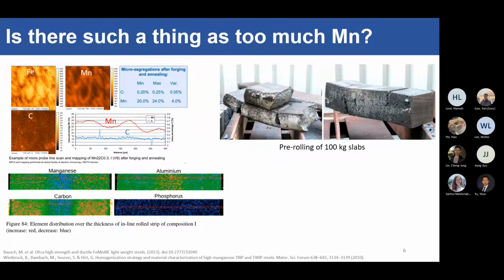If you don't homogenize it properly, you just decide, okay, you know what, screw this, we'll just roll it anyway. Your ingot breaks. So you have very poor hot ductility. But if you try to homogenize it properly, and even if you do manage to roll it, can you see you still have very large segregation of manganese, aluminium, carbon as well. So in fact, it's extremely ironic that the high manganese content, which enables the TWIP effect, is also what's hindering the widespread commercialization of these high manganese TWIP steels.